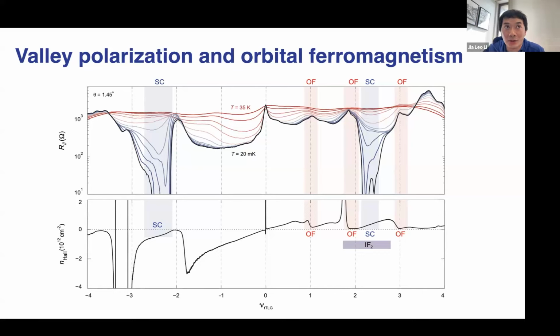That's one. And two is that valley polarization could couple to some other experimental parameter without having to have a magnetic moment, right? So for example, a large DC current bias could switch the valley. There's some kind of coupling there. Or a thermal cycle does switch it and gives you some hysteresis. So the system has some ability of choosing between degenerate states. That sounds to me like the sample has some inhomogeneous environment that it lives in that would spontaneously choose a valley.